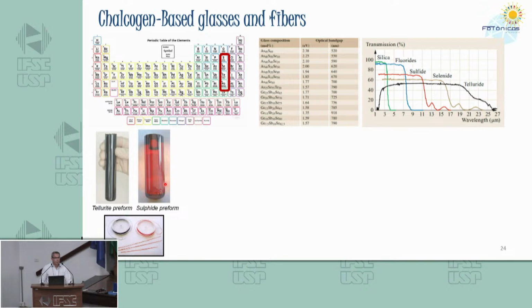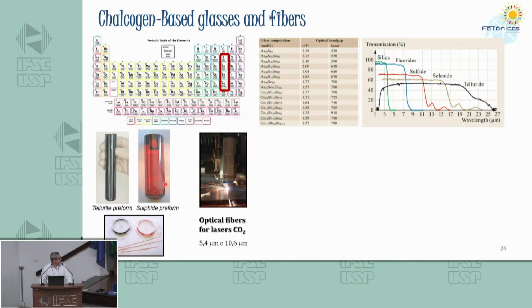Why could this glass be used to produce lenses to see in the dark? As Andrea told us today, you can use a trick: you can dope it with erbium, and then the image that you see in gray scale in the infrared can be passed by up-conversion. You can see it in green, for example, so you see a colored image, but usually it's in gray scale. This is also used for optical fibers to detect CO2 lasers. I don't need to tell you the importance of controlling CO2 nowadays. It's quite important in all industries around the world concerning the greenhouse effect.